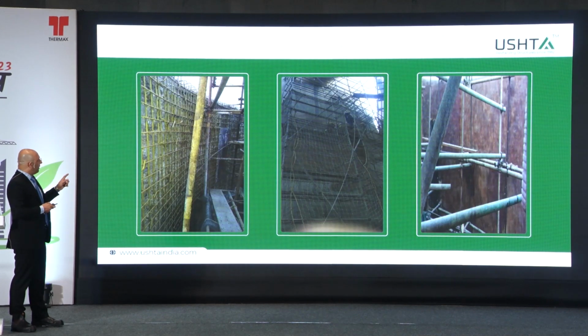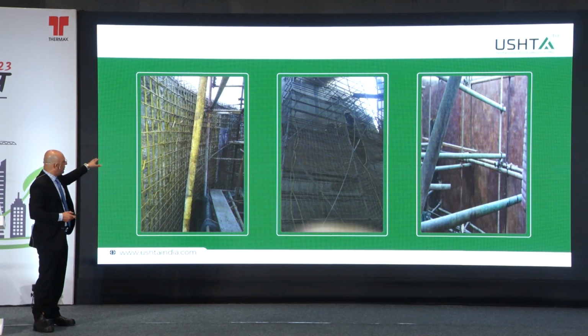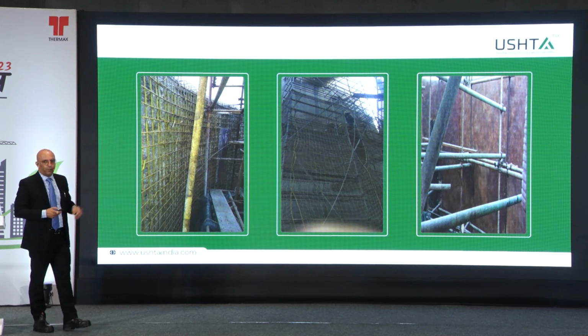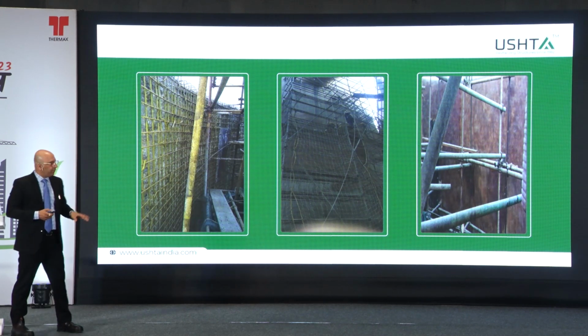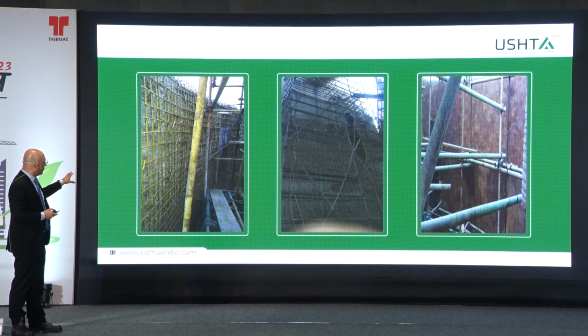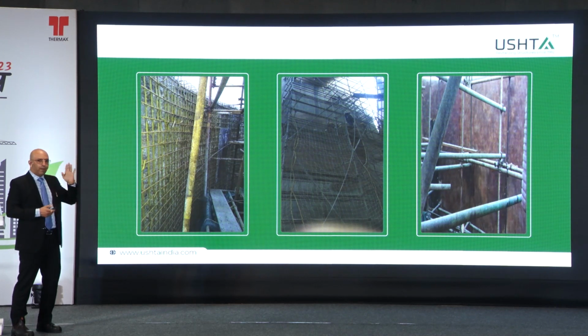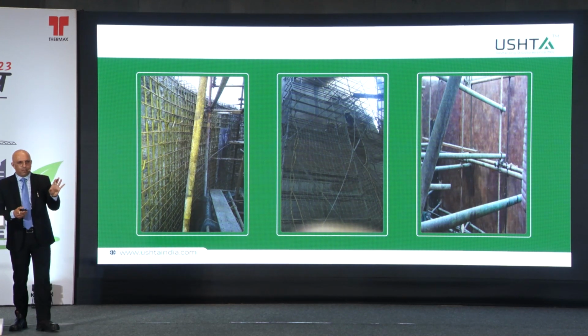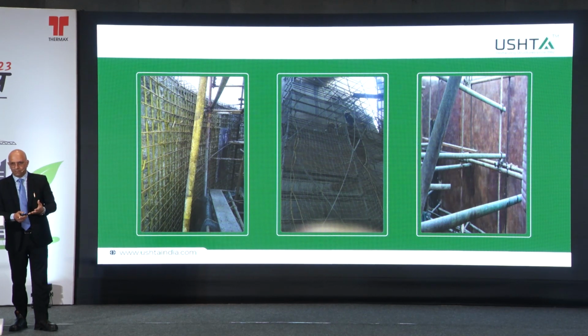And the main problem was the top concrete. Because of condensation here, the top portion of the concrete also had corroded and there was no steel left. So we replaced that with a normal steel, coated steel. And later on we repaired it by a resin mortar, because had we used cement mortar, it wouldn't have even lasted for 1 month. It would just debond.